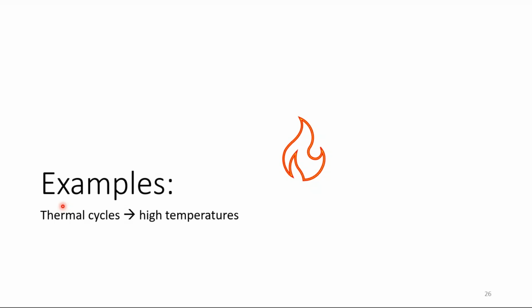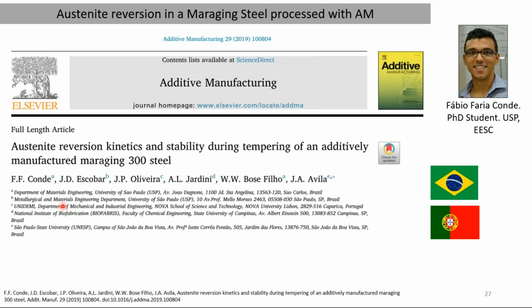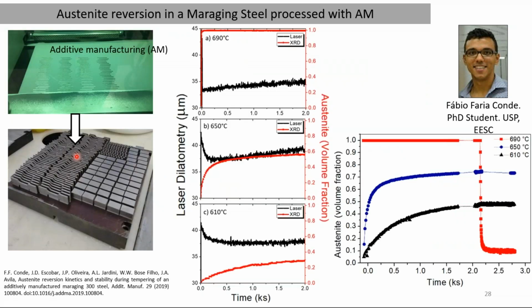Let's start with the thermal cycles at high temperature. This is a study conducted by Fabio Faria Conde. He is a PhD at the University of São Paulo. This paper was published in collaboration with a colleague in Portugal, João Oliveira. In this paper we used a maraging steel manufactured by additive manufacturing, and we studied the kinetics of the austenite reversion. We produced the samples by additive manufacturing, and we got these dog bone samples.